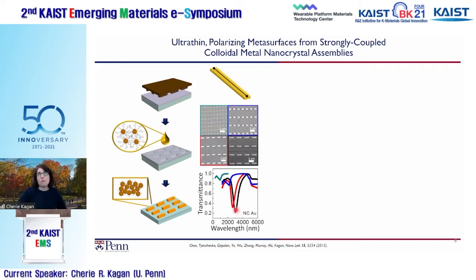And so, of course, because they're also rods, this resonance is also a longitudinal surface plasmon resonance, right? It really has a direction to it. And so it gives you an opportunity to really control and play with polarized light. The idea is that if the light is polarized along this direction, you'll see the transmission resonance here. But in the transverse direction, it would be someplace much further to the blue.